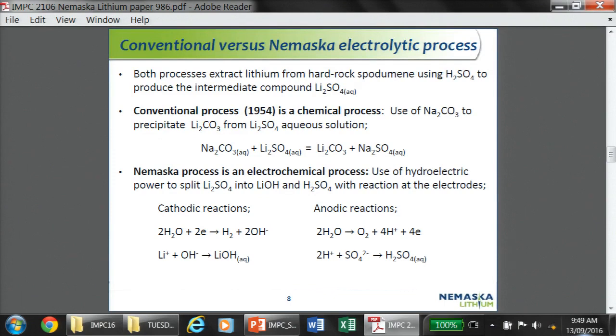If you look at the conventional process patented by Lithium Corporation of America in 1954, this is a chemical process, by opposition to the Nemaska process, which is an electrochemical process. The conventional process uses soda ash. In both cases, you extract lithium from the spodumene using sulfuric acid, producing lithium sulfate as a precursor that you transform after that to obtain the lithium raw materials. But the conventional process uses sodium carbonate to precipitate lithium carbonate, because lithium carbonate is less soluble than sodium carbonate.